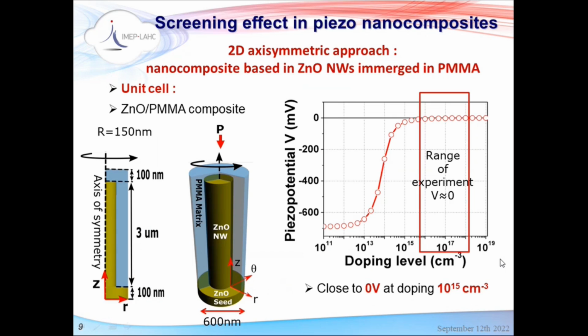So we tried to do that in the past. So we include dopings in these nanowires. We surrounded by the polymer again. And what we can obtain is this potential in function of the doping level. So here, in this red square, are the typical doping concentrations that we can find in experiments. So this is negative, but consider it as absolute value. So you can see that in this range of experiments, the actual potential that you can obtain is 0. So you can tell me, well, it's useless, this composite.